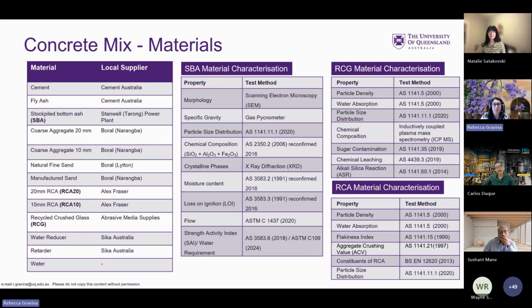When it comes to the material characterization for the stockpiled bottom ash, the properties that we're interested in are the morphology of the material, the specific gravity, the particle size distribution, and the chemical composition, and we do an analysis for that. What are the different crystalline phases? We've also looked at the moisture content, loss on ignition, flow, and the strength activity index. It's quite clear here what test methods we've followed and what procedures have been adhered to.